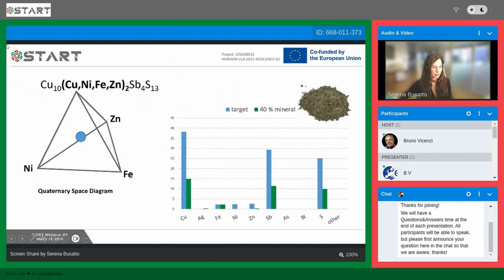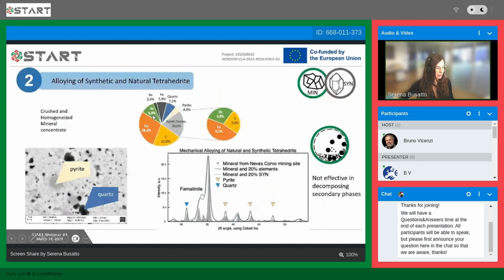So the rest needs to be balanced by adding synthetic elements. Of course, we count silver together with copper. And in case there are arsenic or bismuth in the composition, we count them together with antimony because we know that they will substitute that site. Okay, then we compensate with synthetic elements to reach the target composition. So this is what we tried.